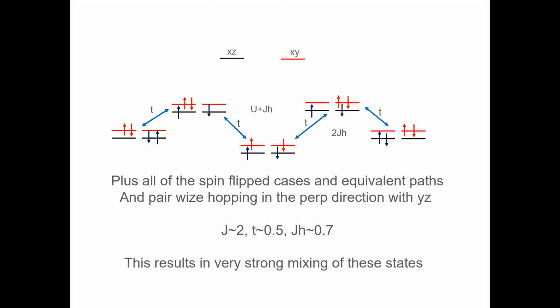So I just want to comment on that because I like this picture very much, because it's not only orbital ordering, which you can explain this way, it's also the sensitivity to the external pressure. Take iron selenium, you can, just by applying pressure, go from 8 Kelvin to 40 Kelvin. You can play with the phase diagram with external pressure, and that's very difficult. It's very much different from the cuprates. And I think this scenario where these high spin, low spin things play a role is a natural way to explain that. And I like it very much. And then the strain comes on top of that, orbital ordering comes on top of that. But that's also a very interesting thing.